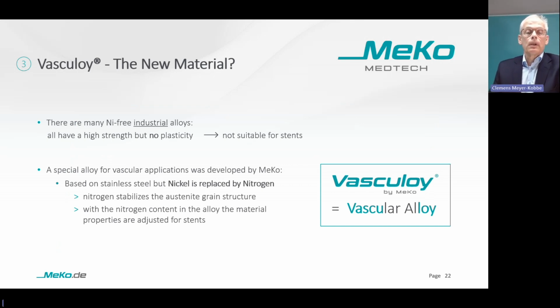First of all, why do we call the material Vasculoy? It's quite simple. As the alloy was especially developed for vascular implants, we combined the 2 words vascular and alloy into Vasculoy. In principle, there are many industrial alloys which are nickel-free. But industrial alloys are developed for high strength. Plasticity is not necessary. No one wants, for example, a screw which can be elongated by 50%. But stents need this plasticity.